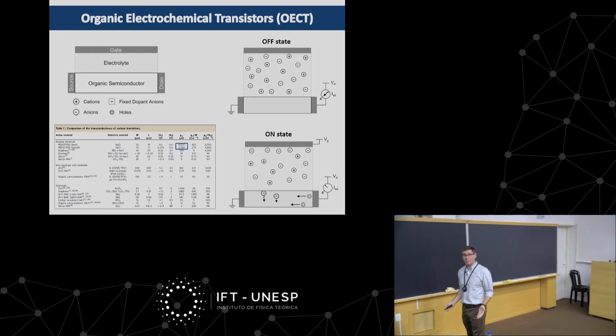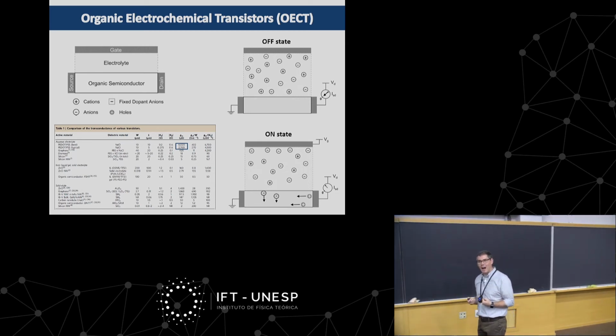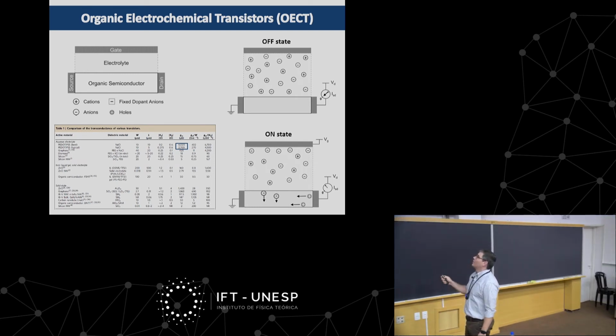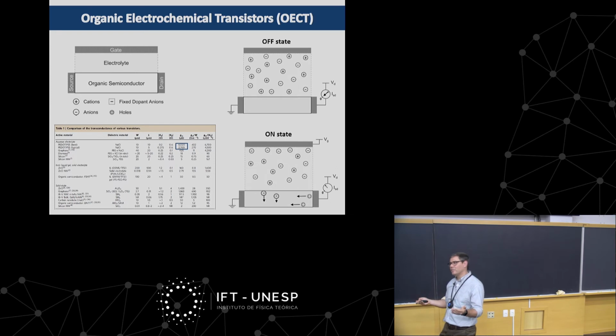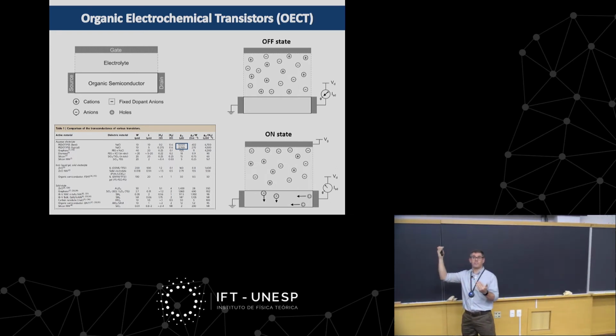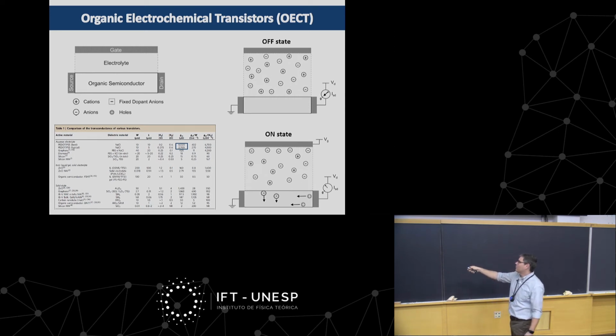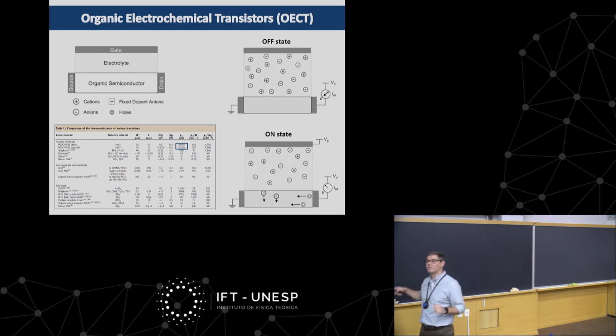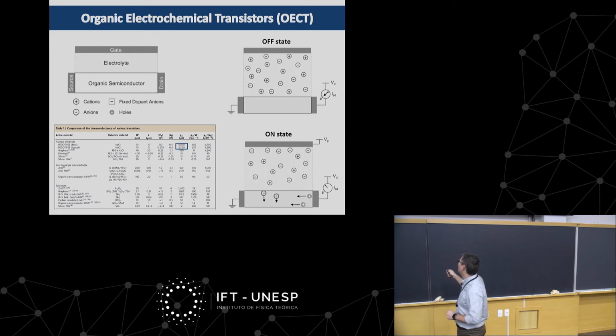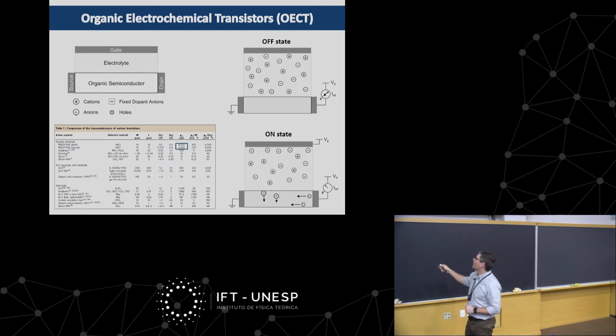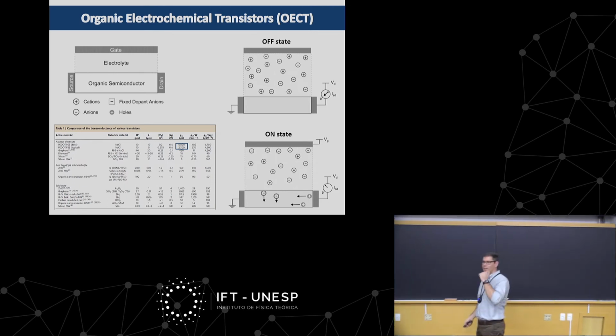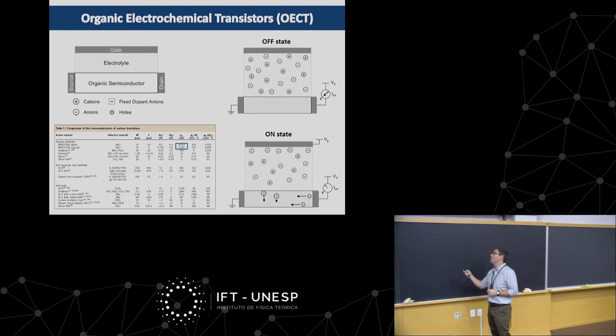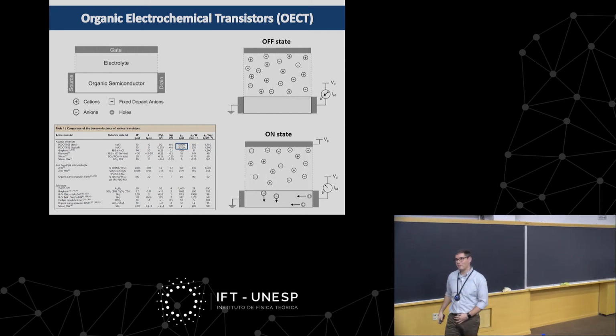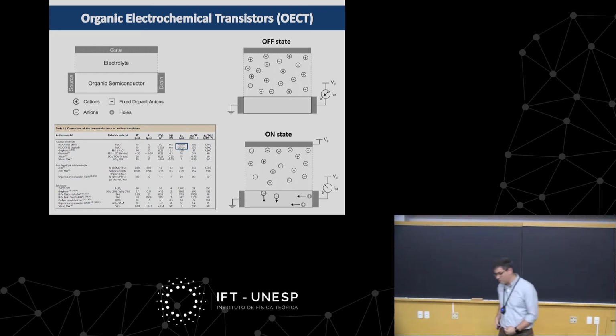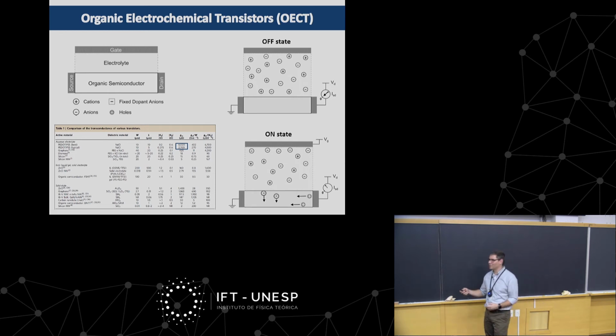So this is huge. And because this capacitance is huge, meaning the ability to uptake ionic species into the polymer is huge, electrochemical transistors made out of polymers have one of the highest transconductances ever published. Transconductance is basically a translation of the on-off ratio of your transistor. So here we have a series of III-V family inorganic materials used to make these transistors. You have transconductance as high as 1.4 millisiemens, and with all these polymers, we can get up to 4 millisiemens. Actually, those numbers are outdated. In my lab, for instance, we just got 6.5 millisiemens, so it's almost 1.5 times higher than the one that was ever published. And I know a group from Imperial College that just published one with 30 millisiemens, so it's 5 times better than mine.